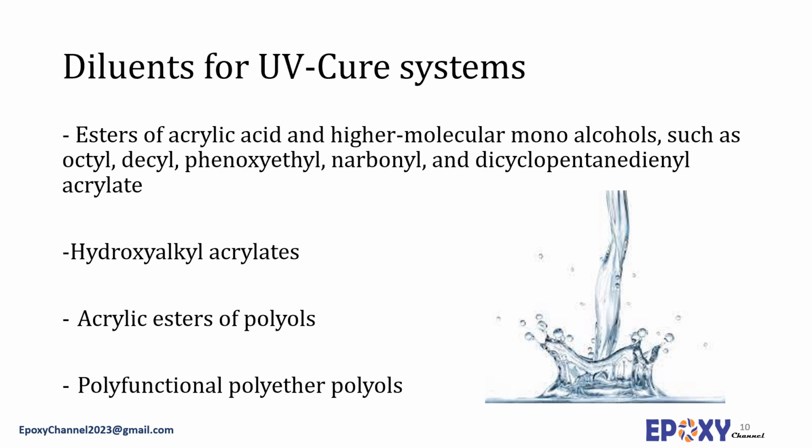Therefore, suitable monoacrylates for UV systems are esters of acrylic acid and higher molecular monoalcohols such as octyl, decyl, phenoxyethyl, norbornyl, and dicyclopentadienyl acrylate. Hydroxyalkyl acrylates are also used as reactive diluents in UV cure systems.